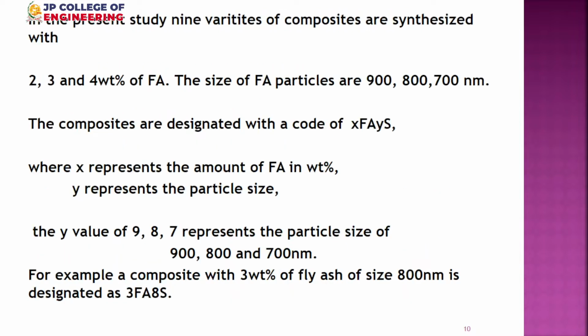Okay, so once we obtain this, then for our subsequent presentation, we have made a kind of code to describe that. We have made 3 different weight percentages, 3 sizes. So accordingly, all the compounds are now given this notation. In the last line you can see 3FA8S. The meaning is 3 weight percent fly ash added and 800 nanometer size. If it is 2FA7S, it means 2% fly ash added and 700 nanometers. Like that, we give some designation for the composites. So in total we made 9 different varieties of composites, checked the properties, and finally zeroed down on the best one for our requirement. That's the idea. Okay, next please.